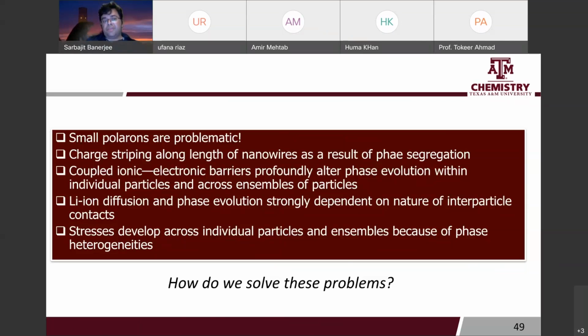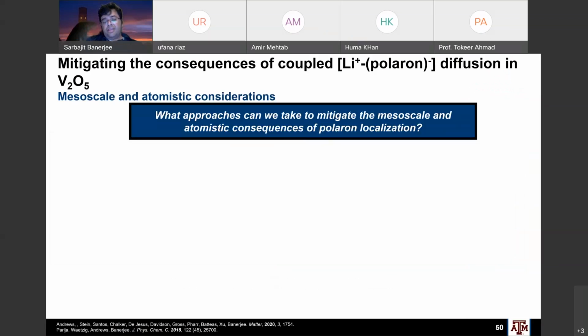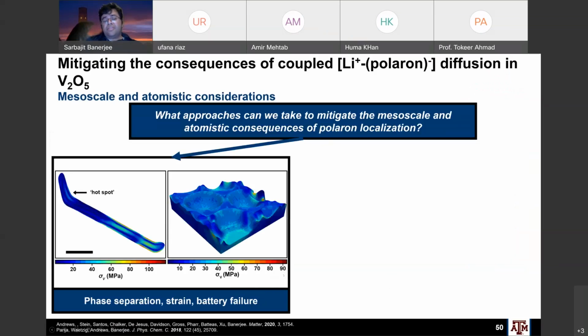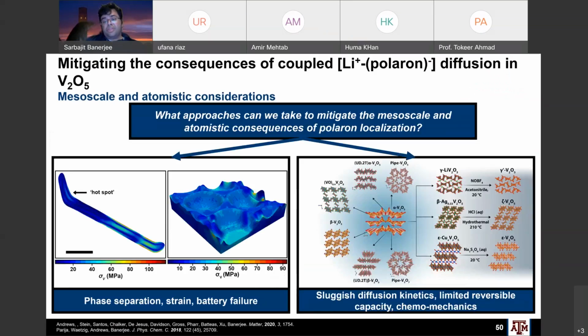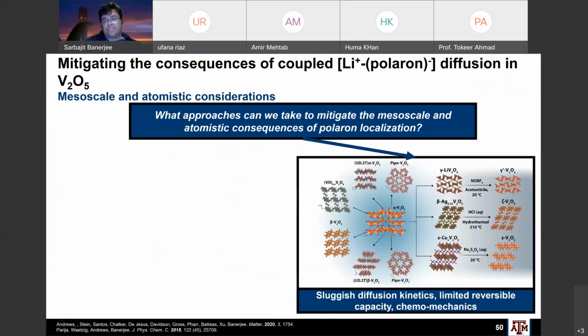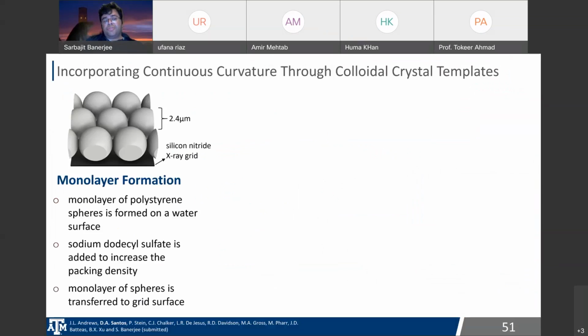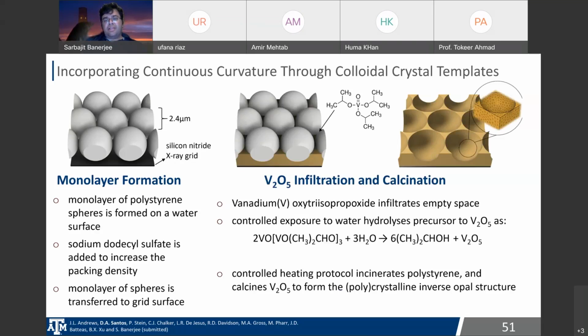So how do we solve these problems? Well, there's two approaches we've tried. This is some work that's cited here, as you can see. One is a geometric approach, where we can essentially play with the geometry of the electrodes to try to address this. The second is a chemical approach where we can play with atomistic structure to address these challenges, right? So essentially, one approach we've done is to play with the idea of continuous curvature to see if we can make an electrode where you've got continuous curvature as a means of getting high capacity as well as very rapid lithiation take place without generating large stress gradients inside the structure, right?